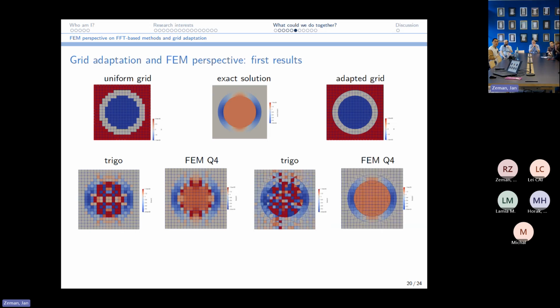So now if I move the nodes and I use the traditional trigonometric Fourier basis, I still have the problems because this movement is too high frequency for the trigonometric basis. So it has trouble capturing it. Whereas if you do it with the FEM discretization, you retrieve almost the exact solution. Okay, which is the traditional behavior we have in FEM, but the resolution is accelerated by the fast Fourier transform. And instead of having, say, 500 iterations, you would have 40.